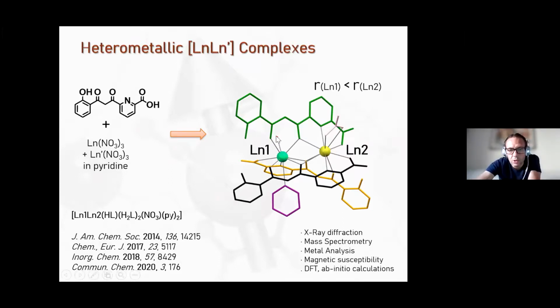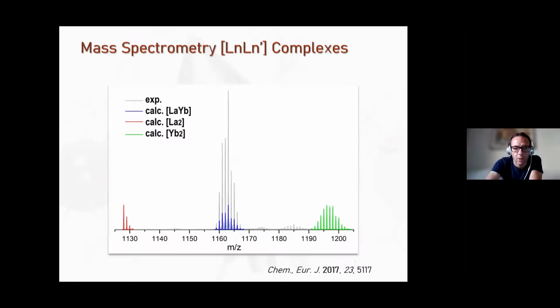It's because in solution, we lose some of these terminal ligands that somehow relax the structure and perhaps diminish, therefore, the selectivity. However, we think this is one of the most, or perhaps the most, selective system based on a thermodynamic process to produce heterometallic lanthanide compounds. So we have exploited that in several ways.